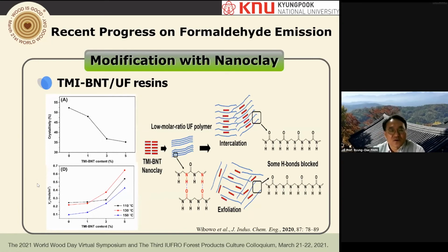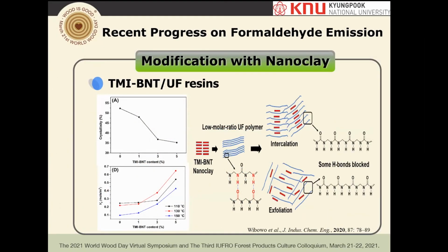We also calculated the cross-linking density of these resins using DMA at different isothermal scanning. As expected, the cross-linking density of the modified resin increases at 5%. That means they are making a three-dimensional structure instead of lamellar crystal structures. On the right-hand side is the schematic diagram of what we thought. We have the lamellar layer structure of the nanoclay and also linear molecules of the low molarity resin, and these have hydrogen bonds between them.